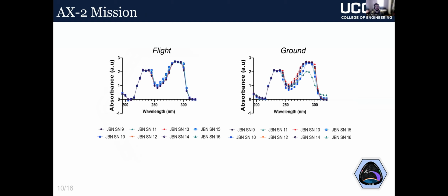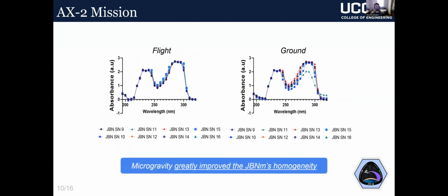So once we got our samples back, we first investigated how assembly in space changed their structural properties. We ran each sample through UV visible spectroscopy, and we noticed that microgravity greatly improved the JBN's homogeneity. On the left, we have our flight samples, and you can see there's very little deviation in absorbance readings across the UV spectrum. While our ground samples on the right show relatively small deviations in absorbance, these are indicative of structural inconsistencies caused by convection.